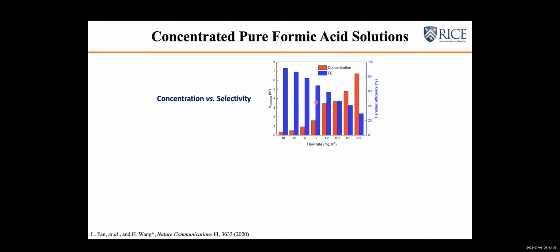This is natural. It's because the middle layer has very highly concentrated formic acid, and CO2 reduction is reversible, right? A high concentration of product will push back against your forward reaction. So that's reason number one. Reason number two is that the middle layer formic acid will cross over to the anode and get oxidized. So your apparent selectivity for formic acid will be low.